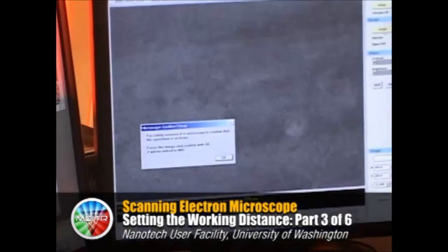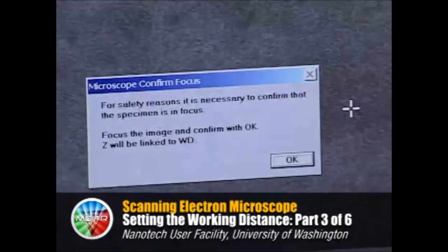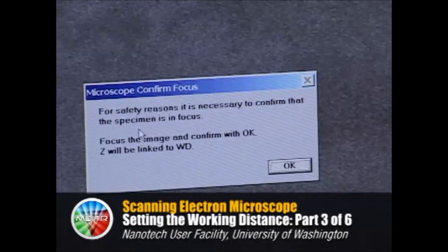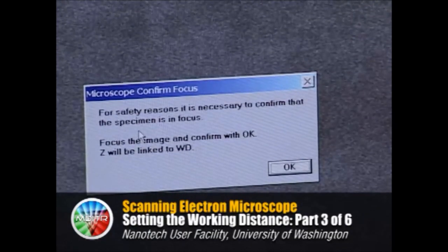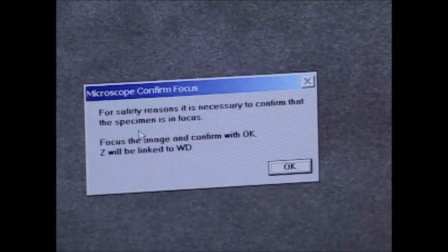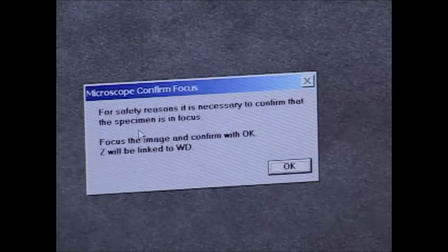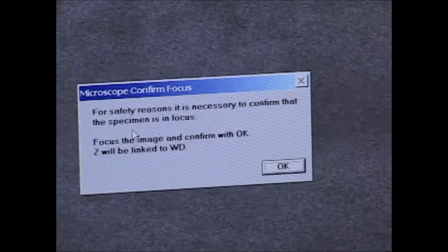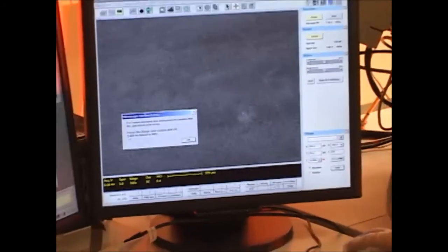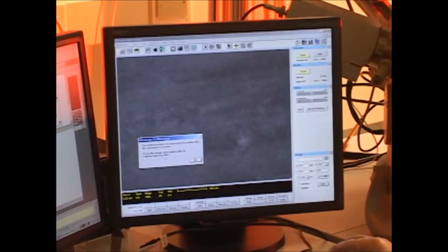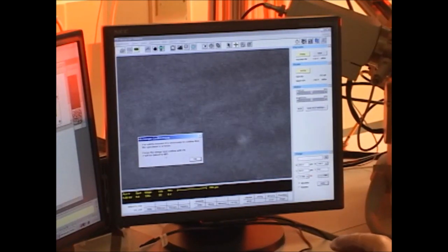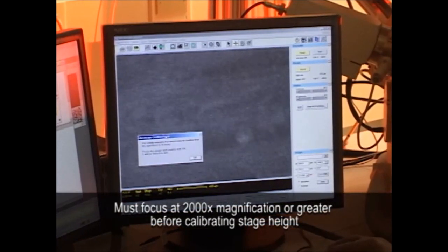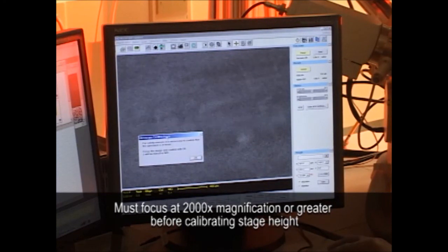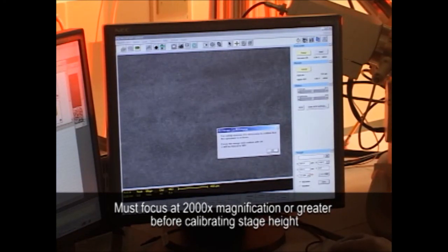When you open the column valve and the beam starts to hit the sample, you'll also see this microscope confirm focus box. The computer doesn't know how tall the sample we put in the chamber is, and so it doesn't know how much clearance we have at this time. But once we've focused on the surface of the sample, we'll be taking a measurement of the distance from the pole piece to the sample itself. And then we can calibrate Z, the stage height position, with the working distance being the distance from the pole pieces to the sample surface where the beam is in focus. If this message box is in my way, I can remove it to another monitor or move it to a different position. But I'm not going to click OK until this sample is in focus at 2000x magnification or greater.